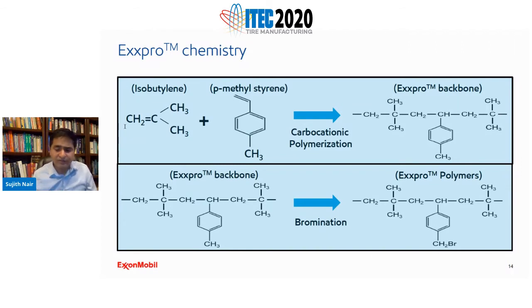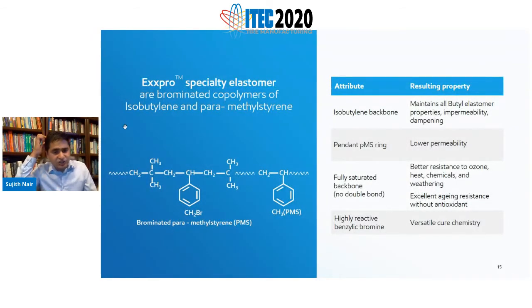Now, a couple of things that you have to note in this is that the chain is saturated. There is almost no double bonds in the main chain. That is one of the biggest advantages of Exxpro. So if you look at butyl, you will still find some amount of unsaturation because of the isoprene in butyl, and that's important because that's necessary in order for the material to cure. But in Exxpro, you've got bromine on that paramethyl group in the styrene block. That's where it cross-links. So literally, you don't need to have any kind of unsaturation in the main chain in order to actually cross-link Exxpro. So that's one of the biggest advantages of Exxpro, a fully saturated backbone.